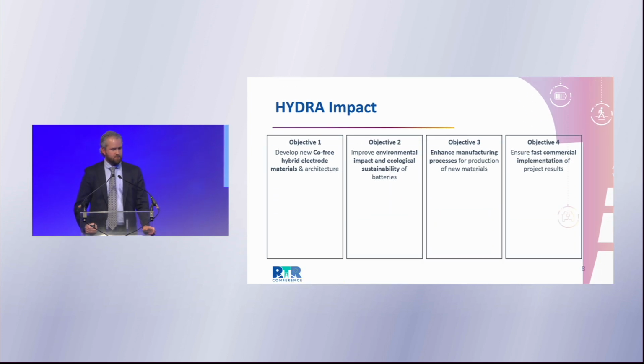So as we come to the end and start to think about what the impact of Hydra has been, we can revisit our objectives. Did we develop cobalt-free hybrid electrode materials? Indeed we did. Reduced the critical raw material content by 33 to 8%, and demonstrated that you can indeed combine high voltage LNMO with high capacity silicon graphite in large format cells.